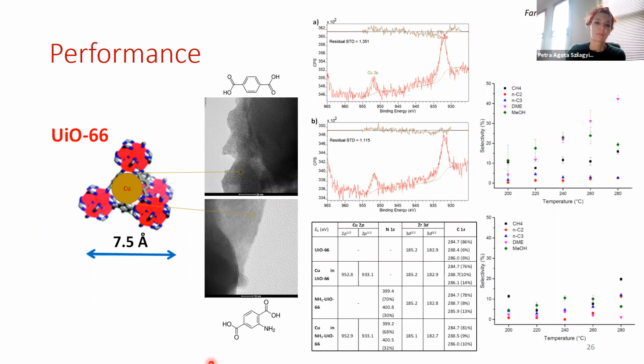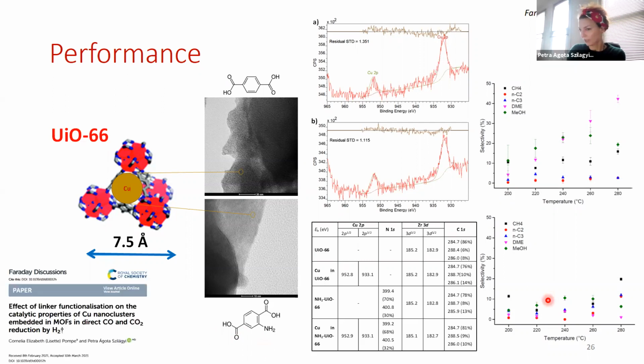Now, the presence of basic functional groups has a long-range effect on the nodes themselves as well, which had been previously suggested, and we could attribute that this has a detrimental impact on the amino UiO-66, and therefore we don't see any significant catalytic activity in this case.